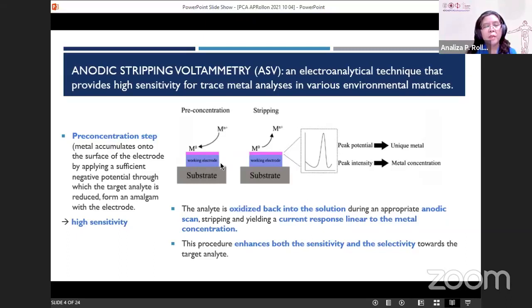So it is accumulated onto the surface of the electrode by applying a sufficient negative potential through which the target analyte metal is reduced, and it forms an amalgam with the electrode. And because of this step, this technique becomes highly sensitive because you can actually do something about the pre-concentration step. So the more metals that you are able to pre-concentrate in here, the better it will be. Although, of course, there may be some limitation as to how you can increase it further.